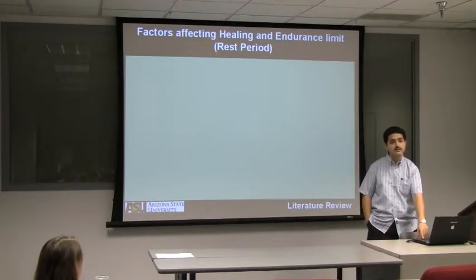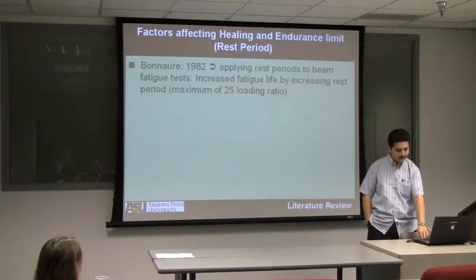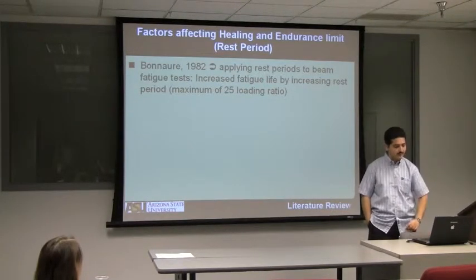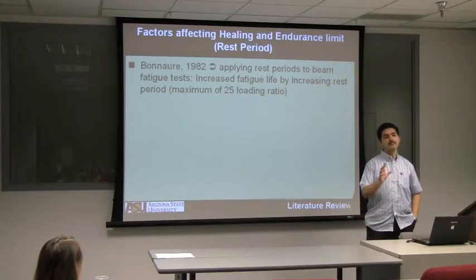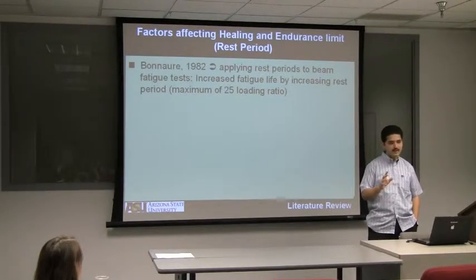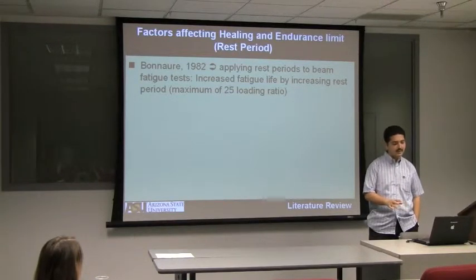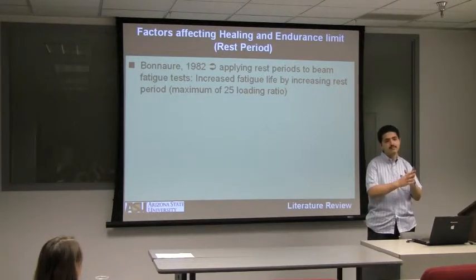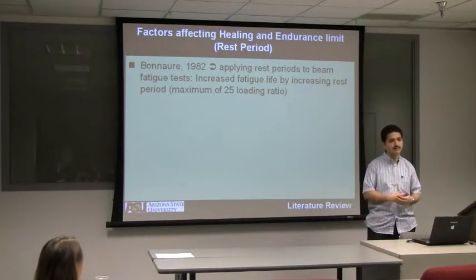Moving to the other factor, which is the rest period, and this is the most important factor in endurance limit. Bonnaure in 1982 also applied a rest period between the cycles, exactly close to what I'm doing right now. And he said he had an increased fatigue life up to, I think, 25 times. So if I apply a continuous test, when I say continuous test, there is no rest period, this can fail the sample, let's say, in 1,000 cycles. If I apply a rest period, it can go to 25,000 cycles, 25 times.